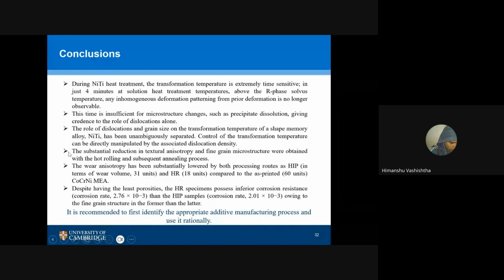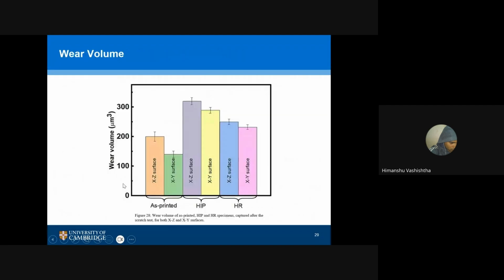Now, coming to the conclusions of the medium entropy alloys, we have minimized the textural anisotropy if you are hot rolling it. That's what we showed in the EBSD maps. The wear anisotropy also has been minimized. The difference between the wear volumes for X and Y, what I'm trying to say is, you can see it. That's the anisotropy in the wear volume with respect to the XZ and XY surface.